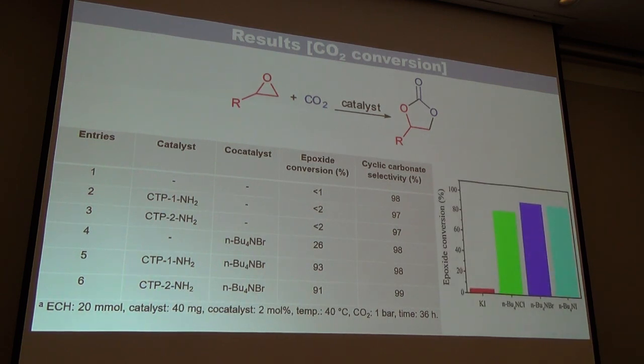Meanwhile, we have also tested a series of nucleophilic additives and their effect in the cycloaddition reaction, and eventually we found that tetrabutylammonium bromide is quite good for this reaction compared to the other nucleophilic additives we tested. So using CTP1-NH2 as well as tetrabutylammonium bromide, the further optimizations were carried out.